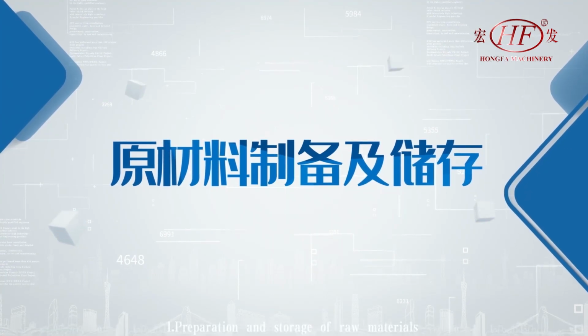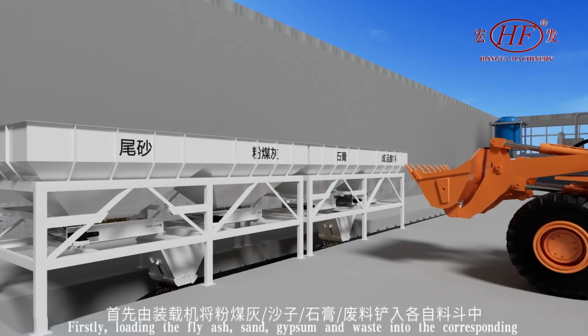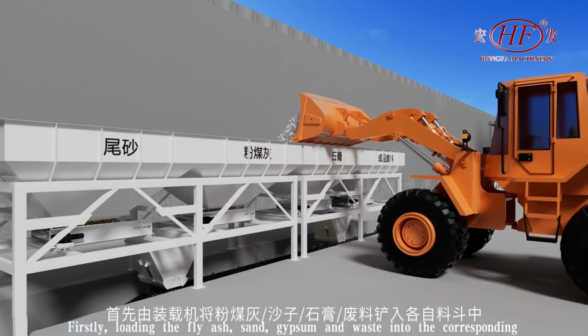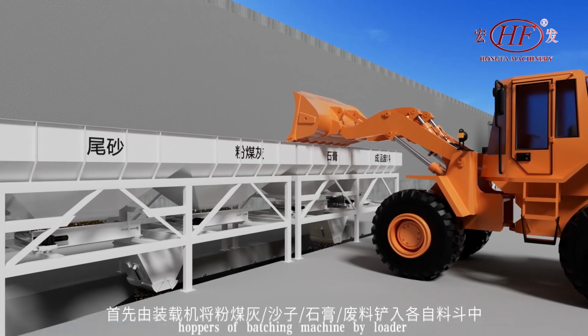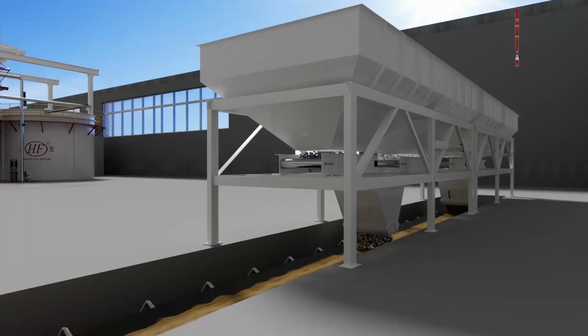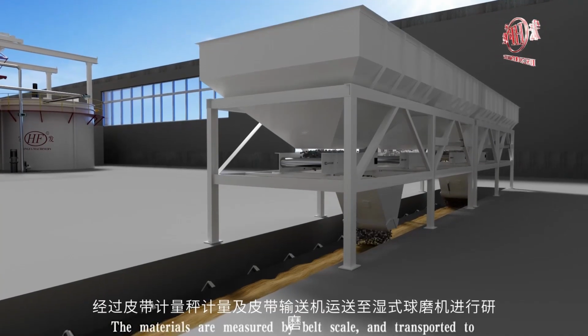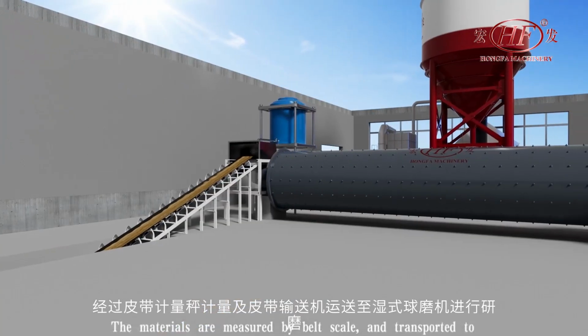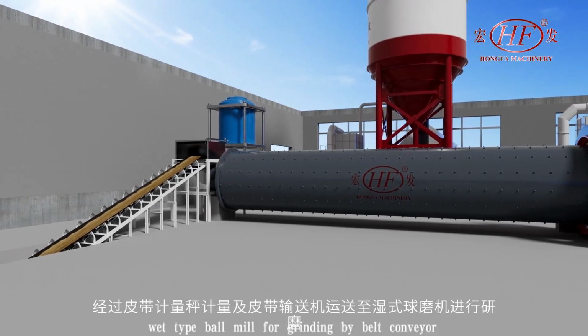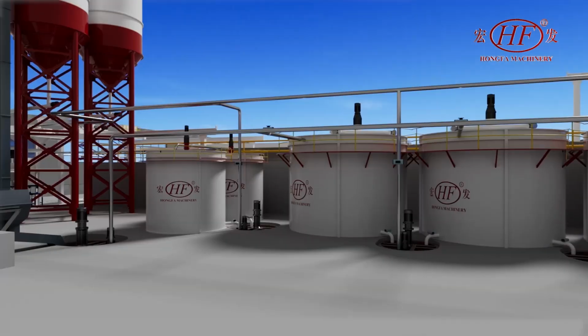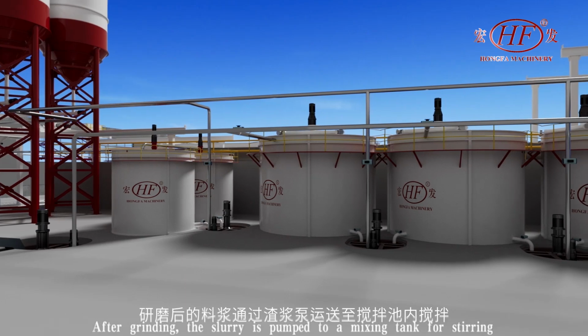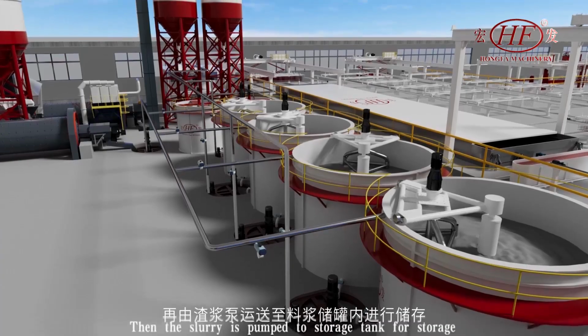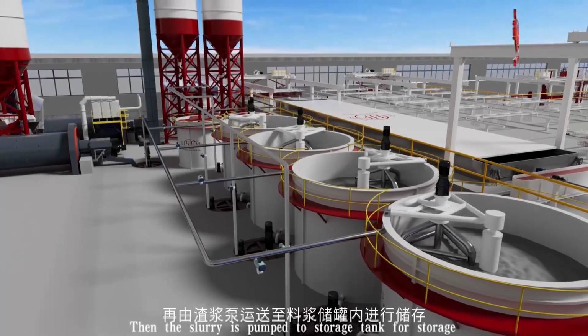1. Preparation and storage of raw materials. Firstly, loading the fly ash, sand, gypsum and waste into the corresponding hoppers of batching machine by loader. The materials are measured by belt scale and transported to wet type ball mill for grinding by belt conveyor. After grinding, the slurry is pumped to a mixing tank for stirring. Then the slurry is pumped to storage tank for storage.